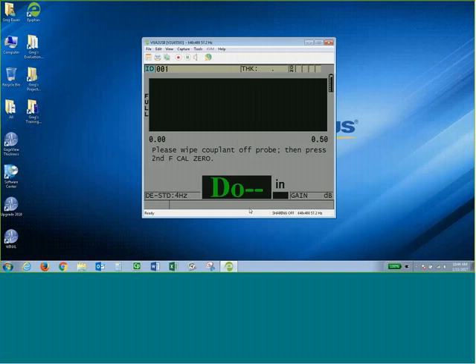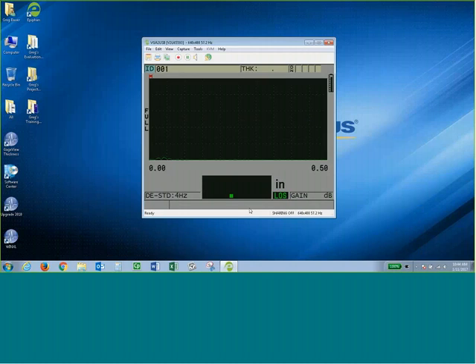So again, I'm going to do my auto 0, second F, cal 0. So the three steps I'll be measuring are 300 thousandths, 150 thousandths, and 50 thousandths. I'm using a plastic card with couplant on both sides to simulate the paint thickness. So if I press the second F key and the zoom key and choose Auto E to E, you'll see when I couple on,